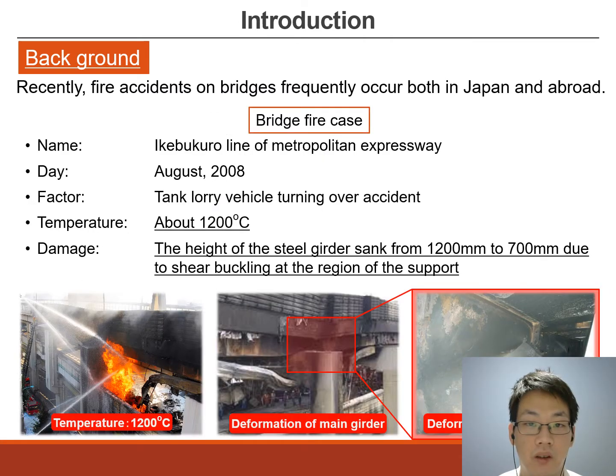This slide shows one example of bridge fire from the previous table. This bridge fire case was caused by an accidental overturning of a tank lorry. As a result of the bridge fire, the height of the steel girder sank from 1,200 mm to 700 mm due to shear buckling at the region of the support. Consequently, this urban expressway was closed for about 2.5 months due to repair works.